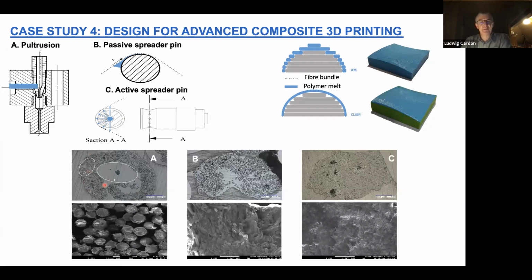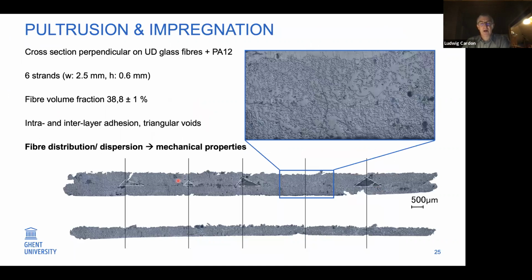So this is the result you can see here. So we have fibers from the pultrusion, which are not wetted, so it's not infiltrated. This is the passive pin, and this is finally the optimal one, the active pin method for impregnation of fibers, either glass or carbon fiber. So after printing several layers, the triangle, what you see, is small voids, which we still have to improve in the process. This gives you a microscope image about the distribution of, let's say, the fibers in layer 1 and the fibers in layer 2. So you can see there is a good distribution.